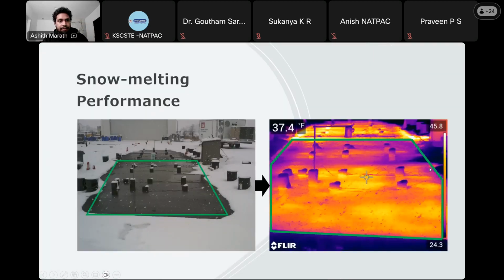With that being said, we constructed the test sections using the mixtures, and we connected the constructed pavement section to a power supply. In the image on the left, you can see how the pavements performed during a snowfall event in New Jersey. As you can see in the image, the pavement was successfully able to maintain a snow-free surface. You can see the intensity of snow on the other side of the pavement, how thick the snow had accumulated, but the sections were performing really well, maintaining a snow-free surface.